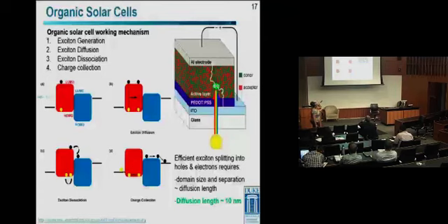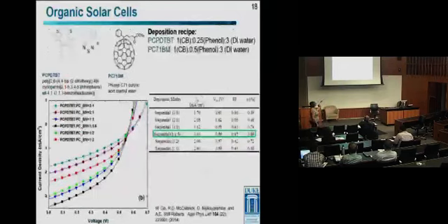So this is an example of a bulk heterojunction. Then you have these interfaces of the donors and acceptors all throughout the active region. For a typical type of material system, this is that low band gap polymer. This is a small molecule, so these are two organic materials. We've deposited these devices here. So in this case, we were just changing the composition of the two components in the bulk heterojunction to find out which was the best for our process.